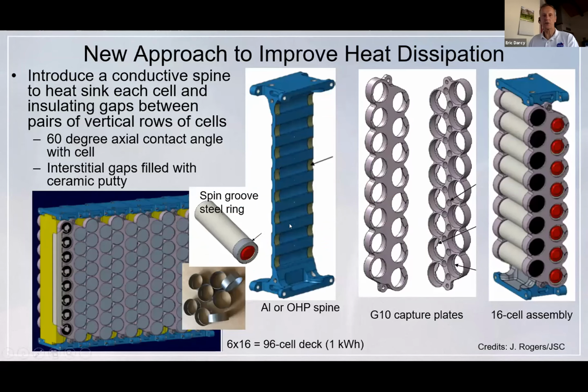So we started looking at a spine heatsink approach with every cell attached by an epoxy bond to a spine heatsink. We looked at solid aluminum, and then the advanced technology I'll tell you about is the oscillating heat pipe. So we put 16 cells in this type of an assembly. And here we ended up with a 60-degree contact angle. And I can tell you that we studied that, and it didn't really matter how big the contact angle was. And the rest of the spaces were filled with ceramic putty, the high temperature ceramic putty material.